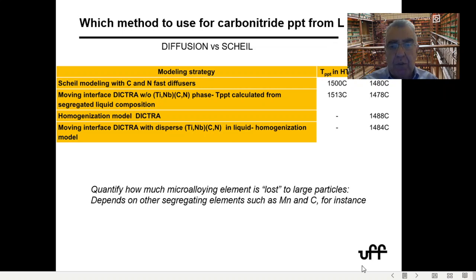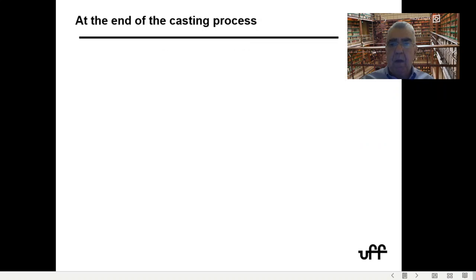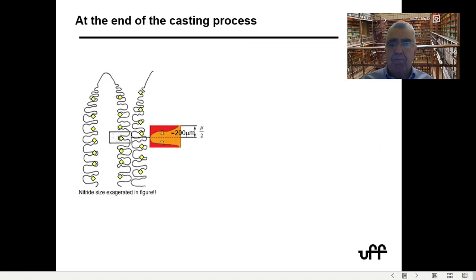So what we can do is quantify how much microalloying we are losing to large particles, because this is never going to dissolve completely again. And then we can also evaluate how the segregation of carbon, manganese, silicon is influencing our titanium and niobium losses. So at the end of the casting process, if we have titanium additions, you can have a very dramatic situation. And of course, I put very large nitrides here so that they're easy to see, but you have nitrides which are not uniformly distributed, and they may also have niobium or vanadium in solution.